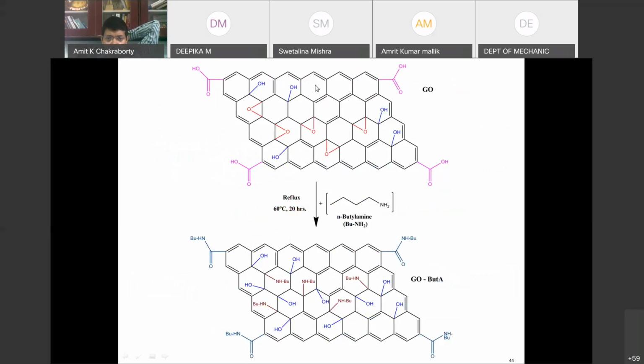So you have the graphene oxide at the top, and after doing the butylamine treatment, refluxing, what you get is a graphene oxide sheet having areas where we have the butyl amine group. This amine group essentially acts like the amine that is also present in the hardener used for curing the resin. So that was the purpose of attaching the amine groups to the surface of the graphene oxide. And then we thought we'll conduct an investigation of interfacial adhesion of this butylamine modified graphene oxide with the epoxy resin system.